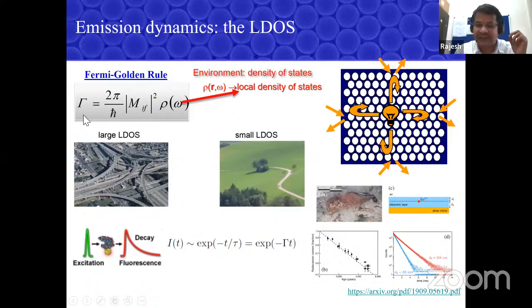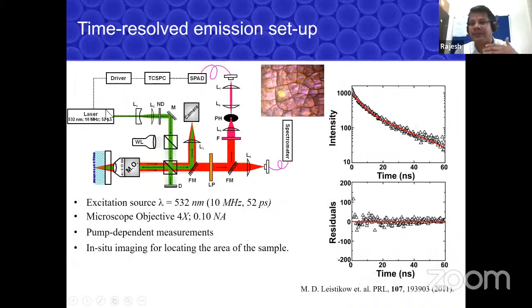So that's what we did next in the experiments. We developed a time-resolved setup where we can measure these kinds of decay rates. We built this setup and measured a typical dye decay rate to check that our system works. You get an exponential decay, and then you fit it with a nice curve to estimate the lifetime. You calculate the residuals, basically the difference between the fit and the original data, and the residual is close to 0. That confirms your fit is quite okay with the system.